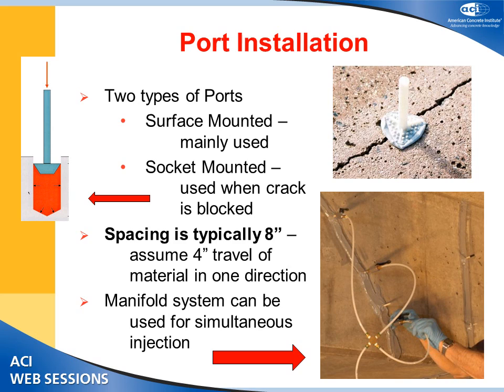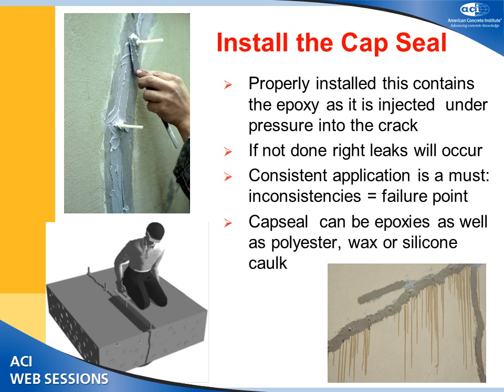Spacing guidelines vary by situation and are not a hard science. You can also inject multiple ports simultaneously using a manifold technique — pumping resin through one source and diverting it through multiple channels. The cap seal installation step seals the surface of the crack so that once epoxy is injected, it stays within the crack. Essentially the cap seal provides a full containment for the epoxy being injected.